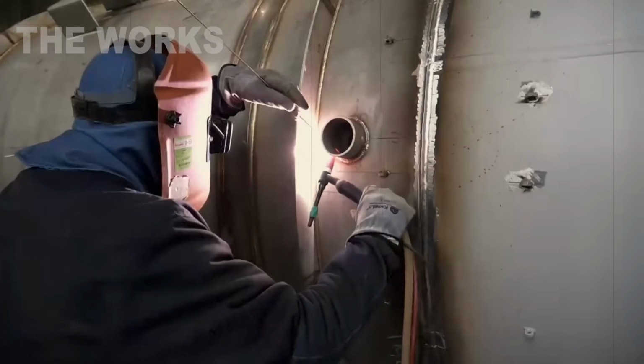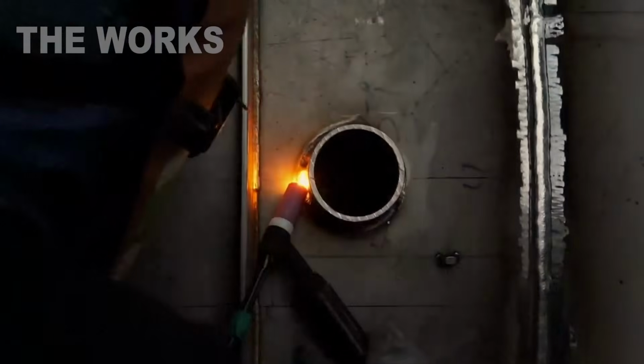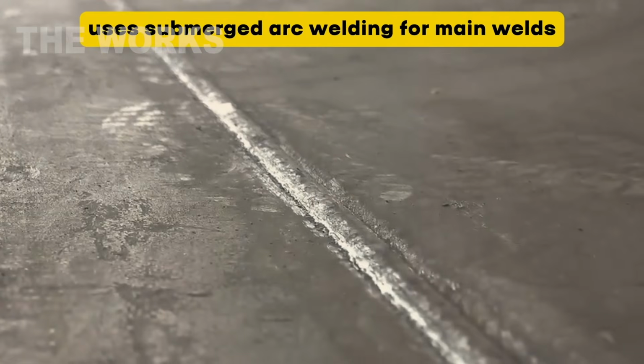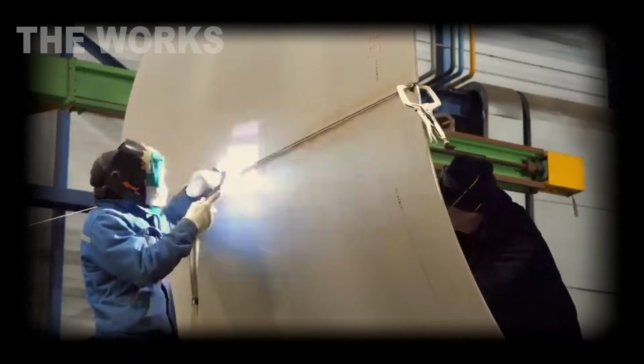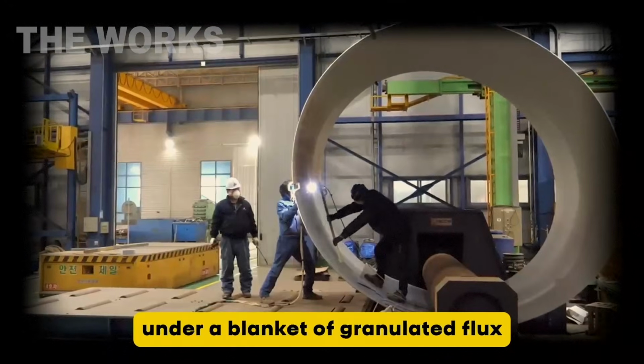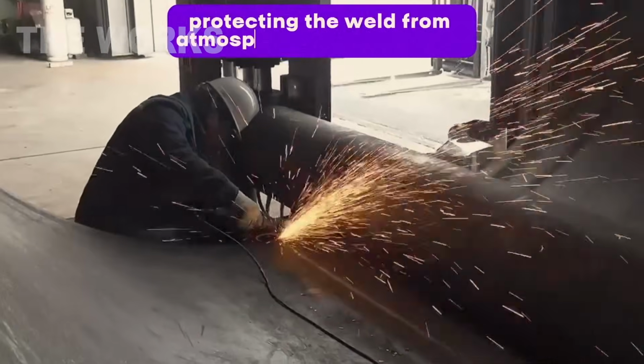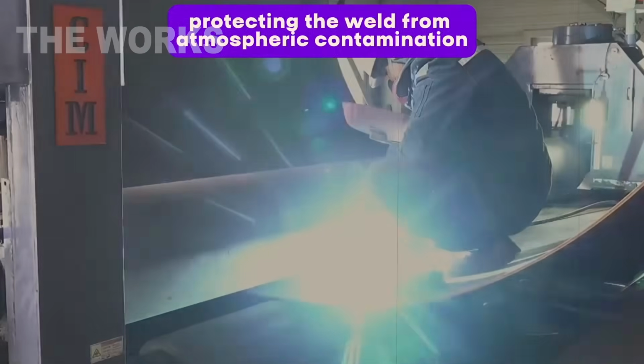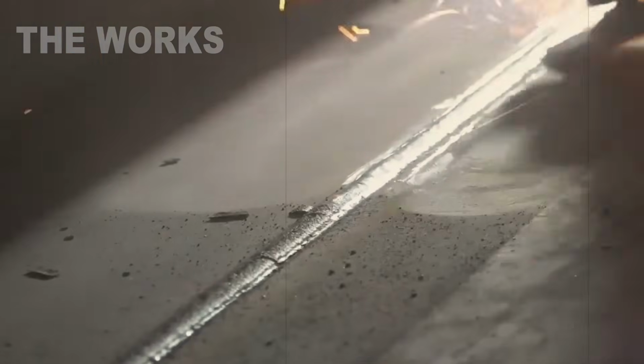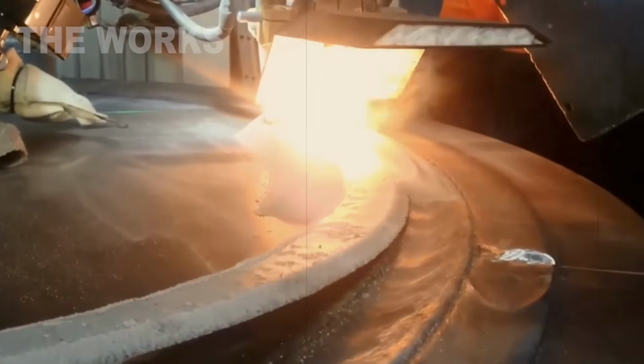End caps, whether they're flat, dished, or hemispherical, get fitted and welded on, and then comes the real test, hydrostatic testing. The completed tank gets filled with water and pressurized above its operating pressure to verify integrity. Any leaks or weaknesses show up here, not during service, which could be catastrophic.